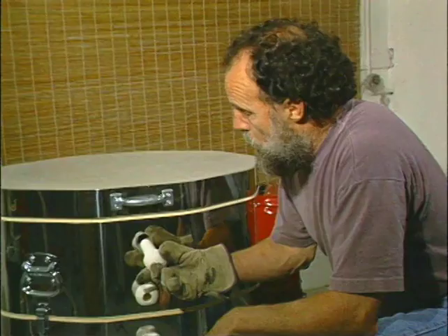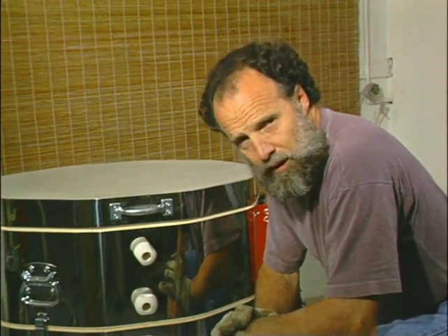By blowing lightly, I've cooled the cones a little bit and you can see them clearly. I can see that the cones are down, so what we have to do now is turn the kiln off and then let it cool overnight, and we can unload it in the morning.